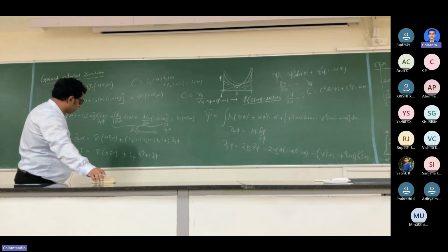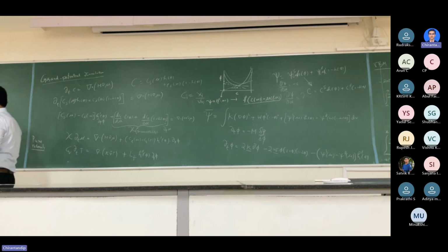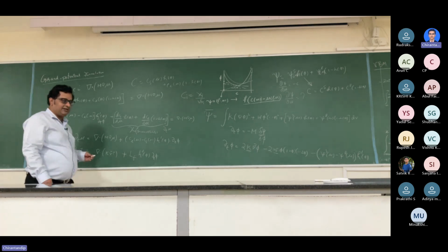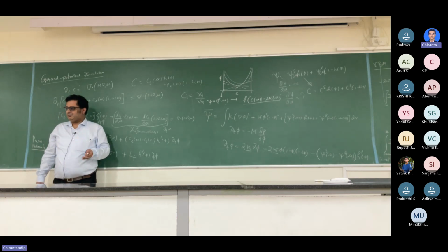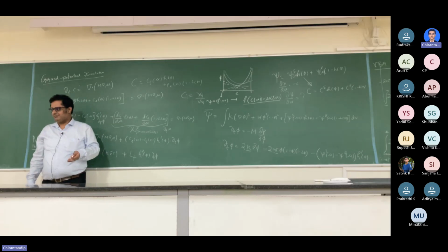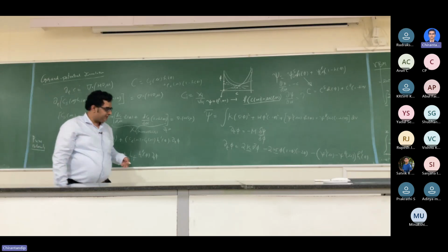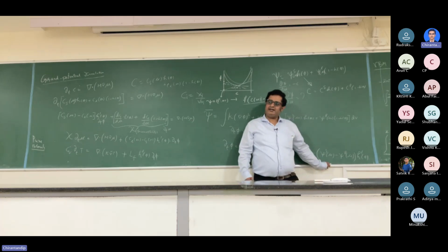Now, is the grand potential unique, or could we have got away with any one-to-one or decreasing function from mu to anything? Just to give you a more thermodynamic perspective of this: the grand potential has a unique place in thermodynamics. Grand potential density is directly pressure. So the difference in solid and liquid grand potential densities is directly the pressure difference.